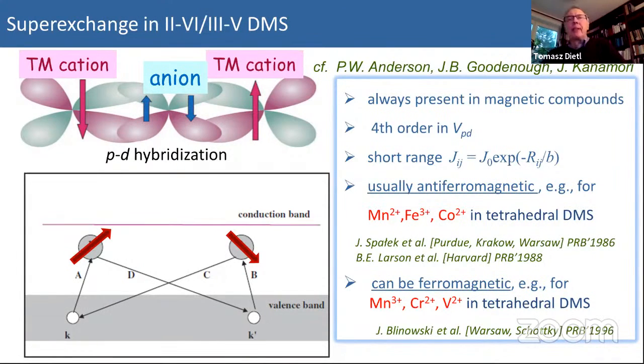If you are interested in a theoretical description, we know that it's related to this p-d coupling between the d wave function and the anion p wave function, short range, and usually it is antiferromagnetic. And in case of tetrahedral coordination, it's antiferromagnetic for manganese 2+, with 5 electrons, for cobalt with 7 electrons, and so on. But it can be in some cases ferromagnetic. And this is the case of manganese 3+, chromium 2+, vanadium 2+. In case of tetrahedral DMS, it would be different from the octahedral situation.